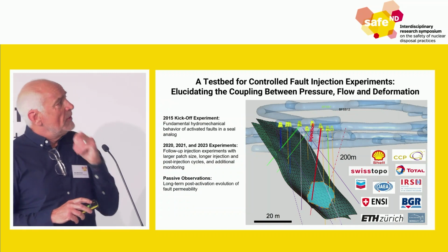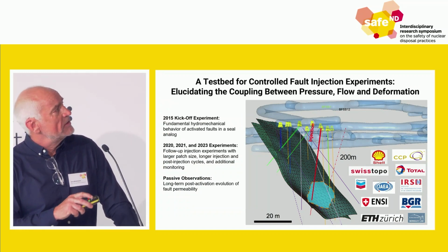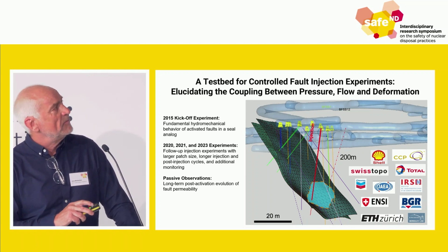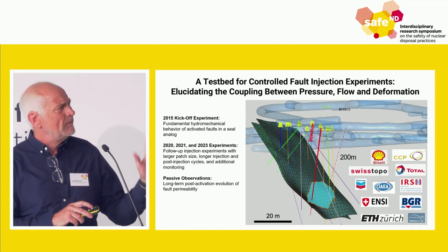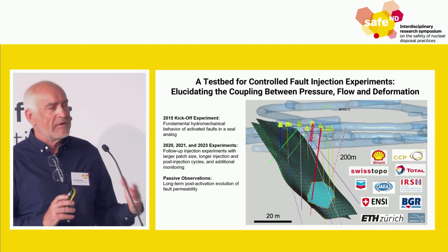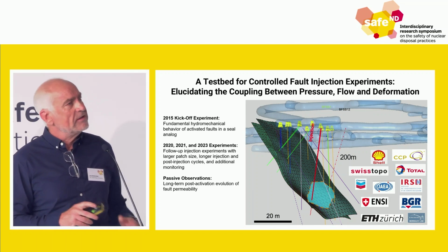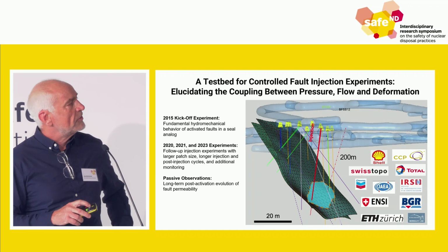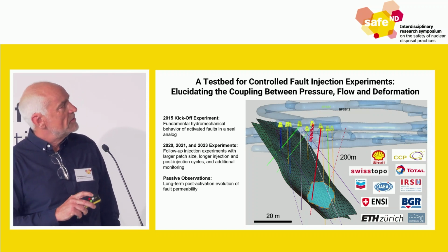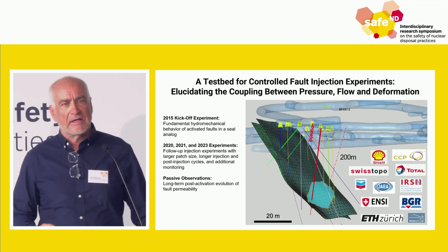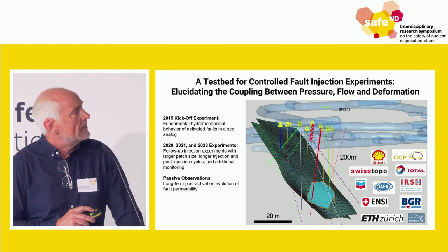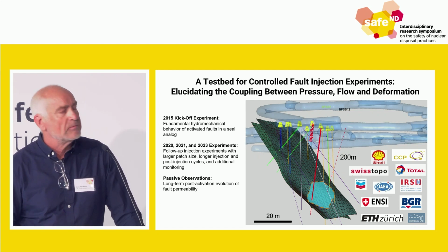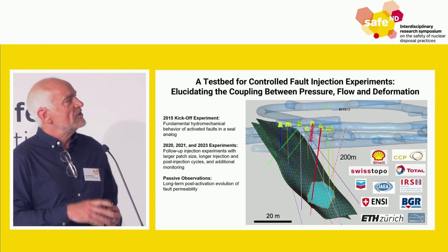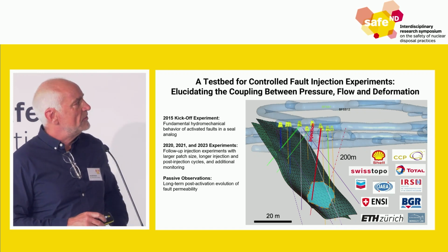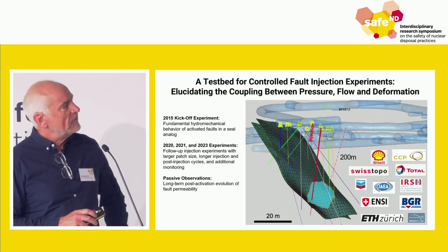So what we then did is we drilled from the tunnels through the fault. We had a 2015 experimental campaign, about 30 to 40 meters below the tunnels, fairly small, just a few meters between injection and monitoring. Then later, in 2020, '21, '23, we went deeper and into a larger fault patch, and also added a bunch of additional monitoring. In between, we did some long-term work - we stopped injecting and then checked what the fault would do in terms of post-activation behavior.